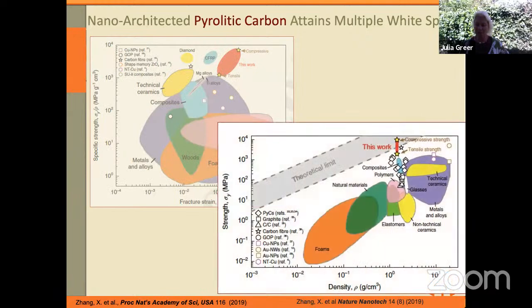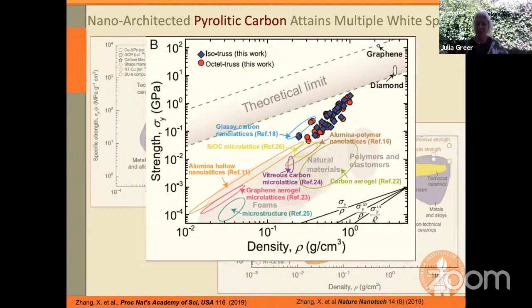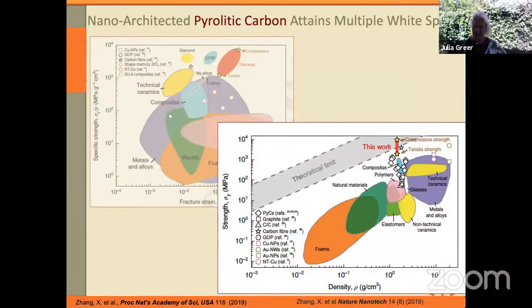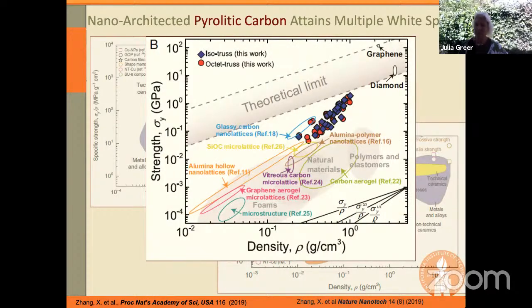Now, the good thing about carbon, and I'm just going to skip right now to here, is that when you plot this strength versus density white space that I keep on referring back to, it turns out that in the limit of higher density, we're able to approach the theoretical limit much better than we were able to do with the hollow alumina nanolattices. So here's where the nanolattices are right here. And you can see that in the case of carbon, we're much more able to get to the theoretical limit. And here, if you look at the strength versus density, here's the tension and compression compared to other carbon-based materials. So there's definitely promise here.